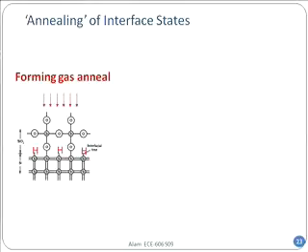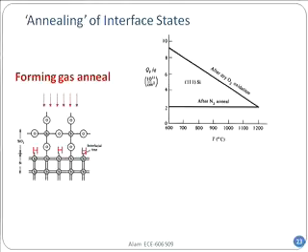And you realize it had one dangling bond. Hydrogen has 1 electron, 1 proton, and it's a small atom, so it can get through anything, and therefore they will come down and essentially passivate all those bonds. And now all the silicons are satisfied. Electrons can go unimpeded from source to drain without being trapped by the dangling bond of silicon.